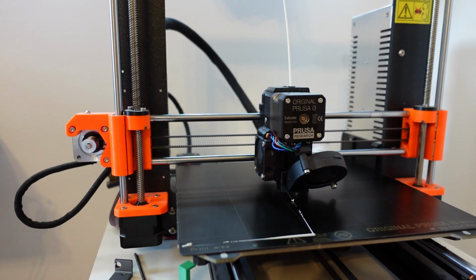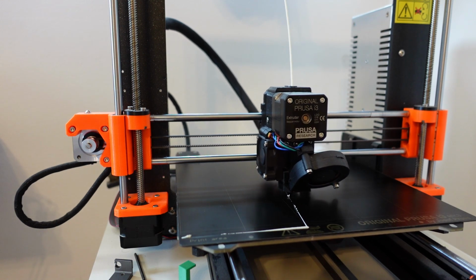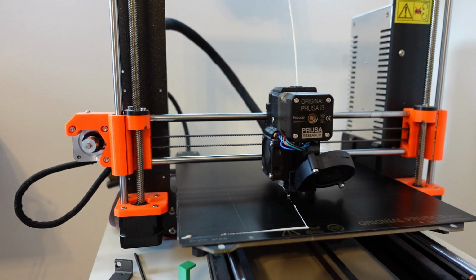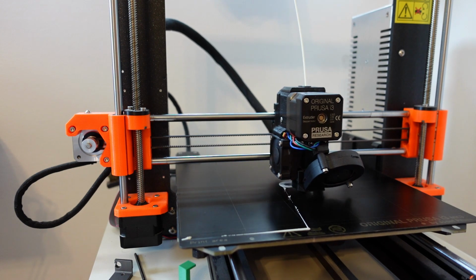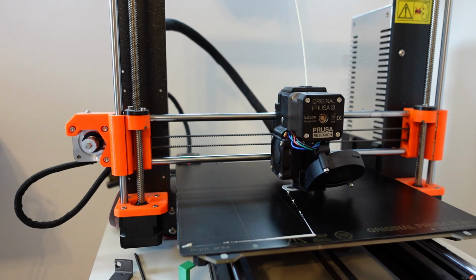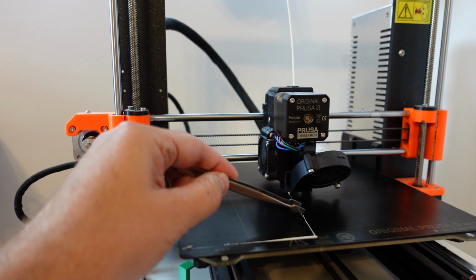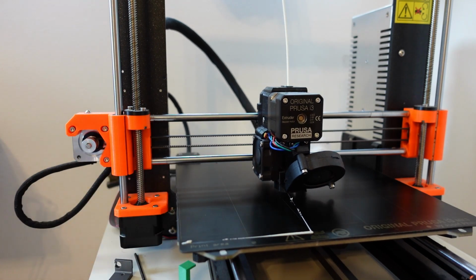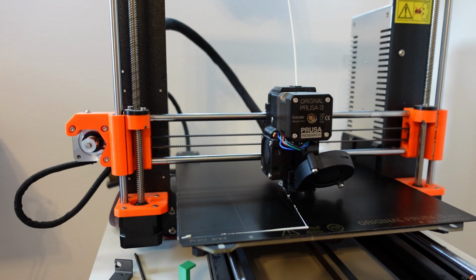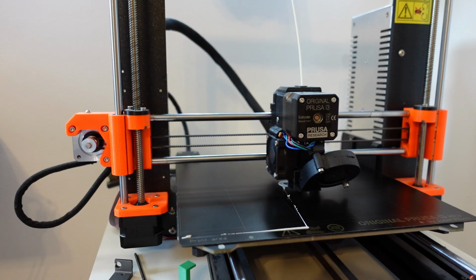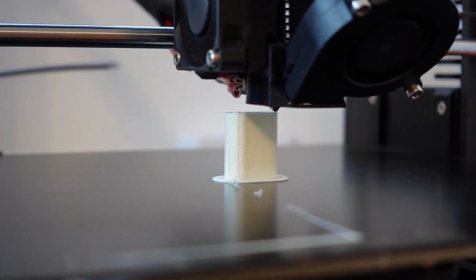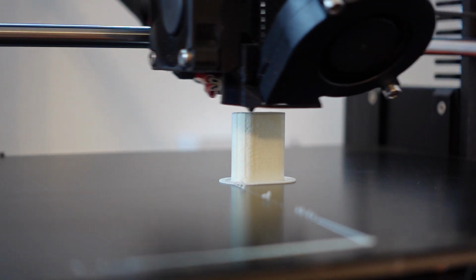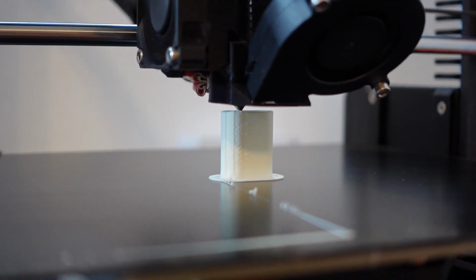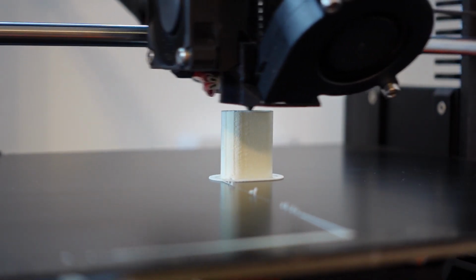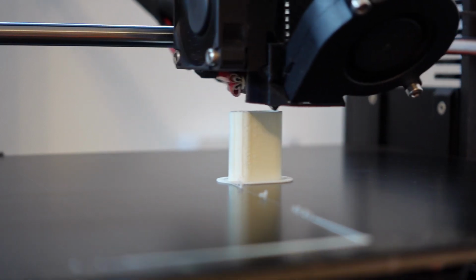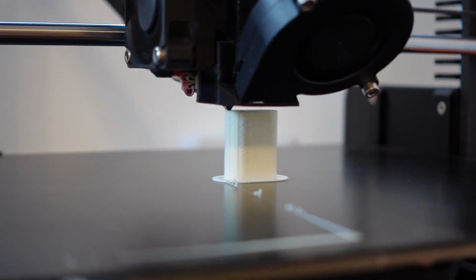There's the brim, super fast because even the first layer starts with 40 millimeters per second. And as you can see here, it would be very big stringing if it were a different object. Since the retraction with this filament doesn't work so well, the seams are very visible. That's why it is important to plan the position of the seams if possible. You can do it in PrusaSlicer and also in Cura.